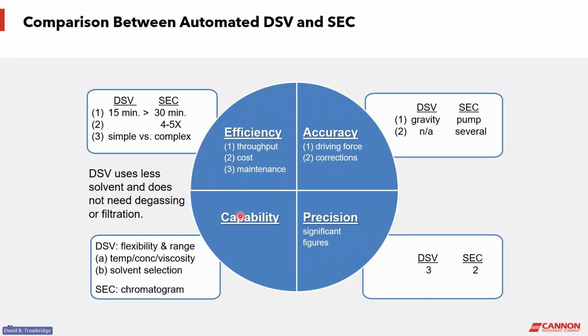And then regarding capability, in the context of flexibility and range, DSV has opportunities to operate at different temperatures, concentrations, and viscosities, and solvent selection as well. These are not easily available in SEC. You can do different temperatures, but it can impact the condition of the columns, and concentration can be varied, but it also impacts the retention time of the chromatogram. So you have to be careful if you try and manipulate these, but in a DSV, it's very straightforward, and you use less solvent, and the solvent doesn't have to be degassed or even filtered. Those are usually required for chromatogram work, SEC work.